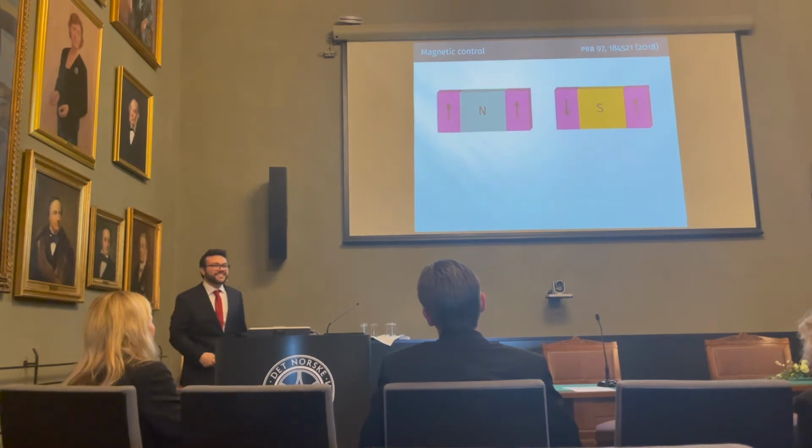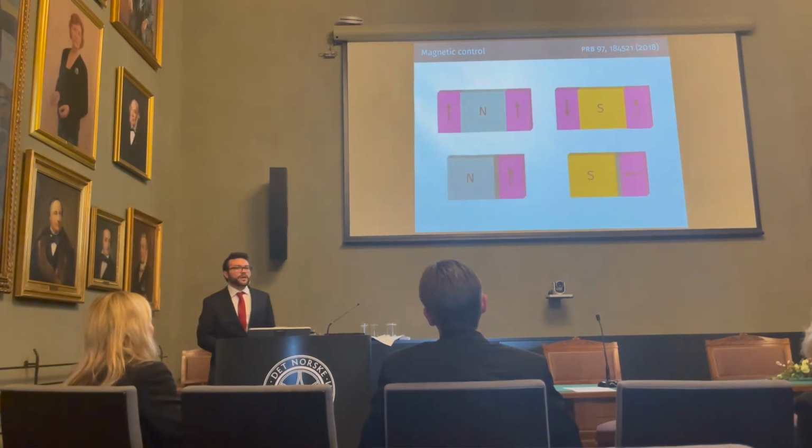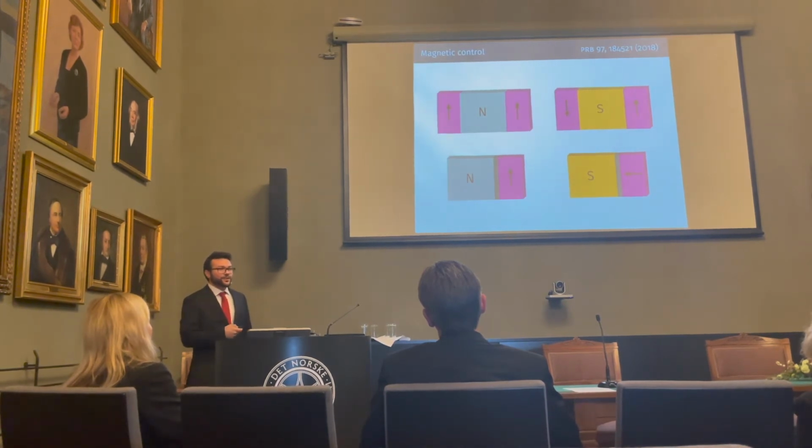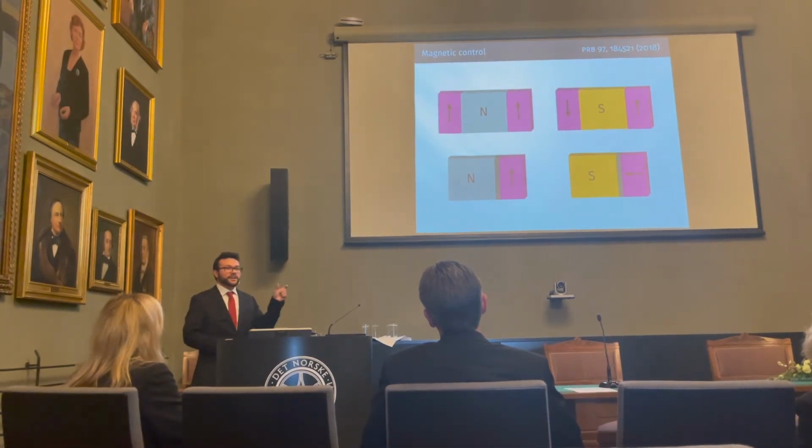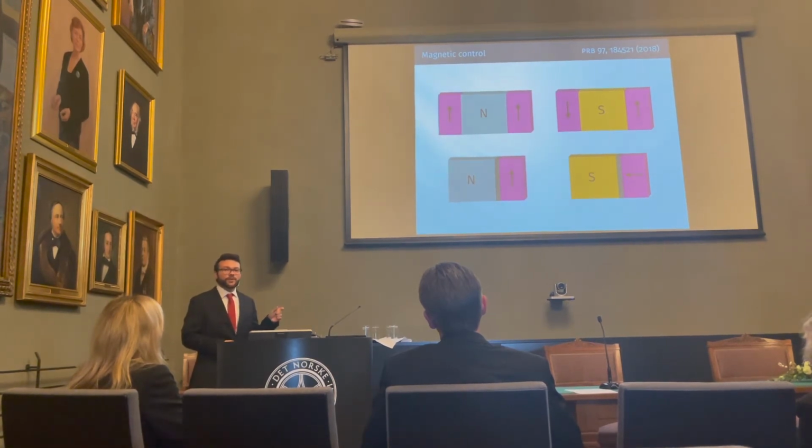so easy. So what we did in our research was that we found a way to do the same using one ferromagnet instead of two. So this was done by placing an extra layer in between, a thin, like 1 to 2 nanometer thick layer of a heavy metal, such as platinum or gold.